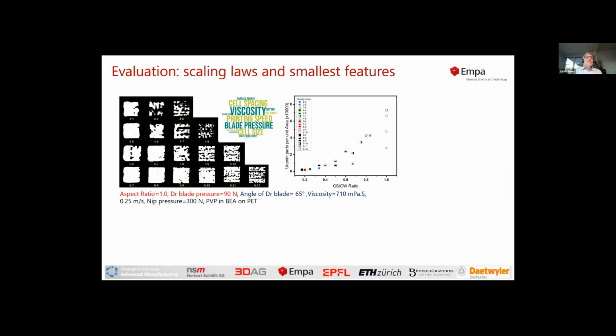So how we do the evaluation: what we're actually looking for are scaling laws and the smallest features we can achieve. These are examples of this evaluation. We are not only interested in perfect pattern transfer, but we're also looking at under which conditions we actually introduce a lot of defects. And what you see in the middle graphic here is that we indeed can find scaling relations when we vary certain parameters in this printing process.